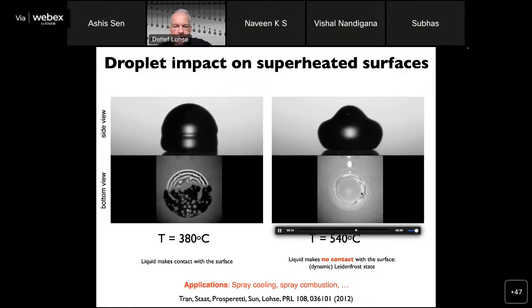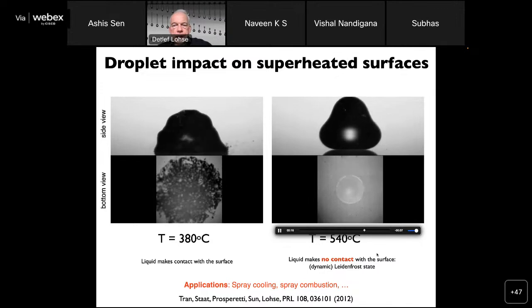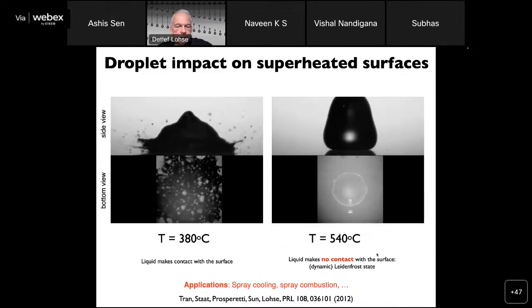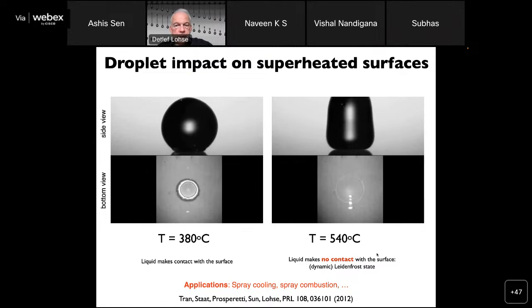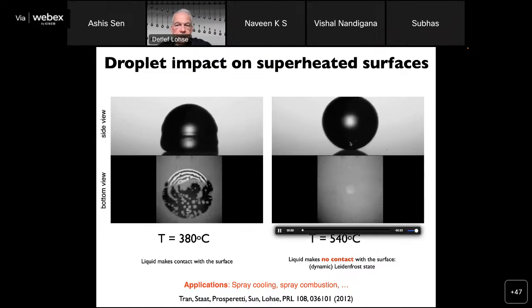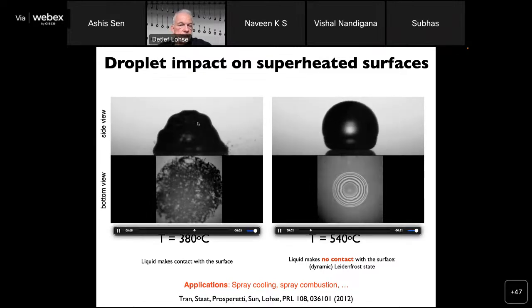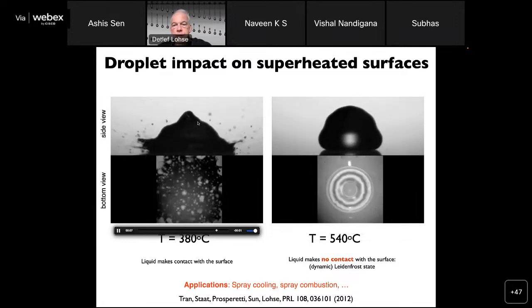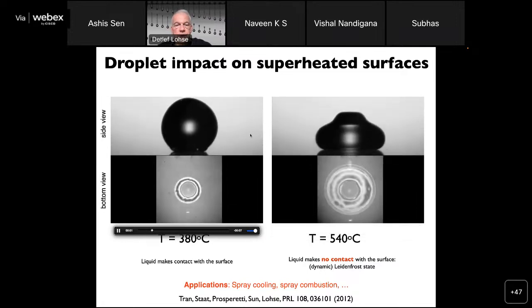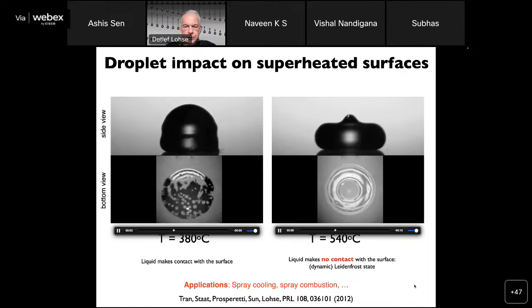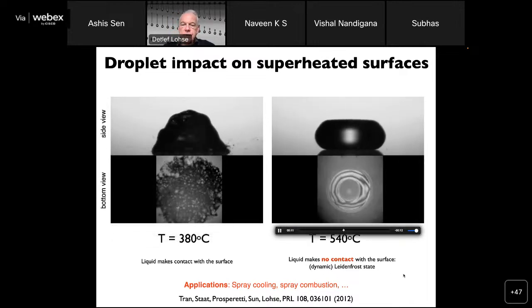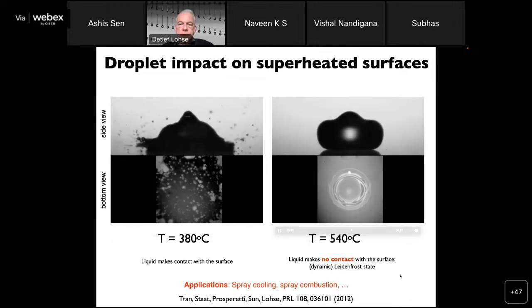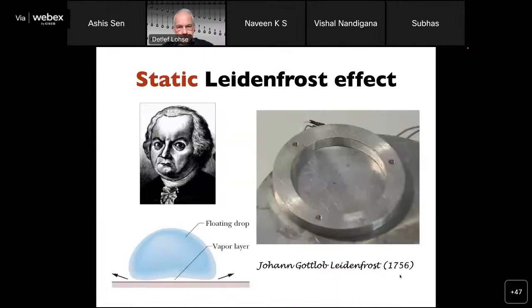no contact at all. And the application of this kind of phenomena is tremendous. So spray cooling, for example, where you really don't want to be in this Leidenfrost state, but you want to be in this state to have maximum heat transfer, but also for spray combustion, all this is absolutely crucial. So we call this here the dynamic Leidenfrost effect because we let the droplet fall on this. So the static Leidenfrost effect has been known for long, in fact, since 1756.